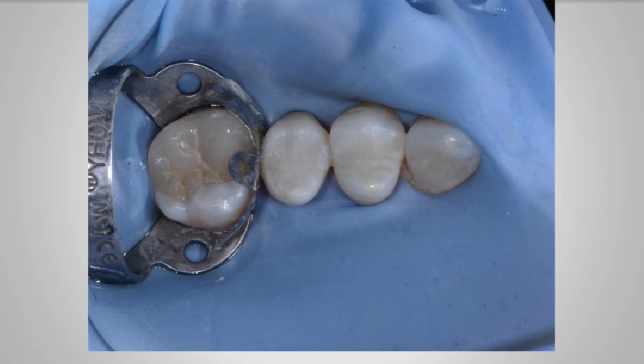And I think one of the things that can happen, you'll know if you're curing adjacent cavosurface margins and you're doing it at the same time. If you notice on both of these cases, we don't have any really major white lines or anything, but if you see those white lines along your restorations, more often than not, that's either a contamination of your adhesive material with saliva or something like that, or it's a stress factor that you've created and you've bonded both sides.